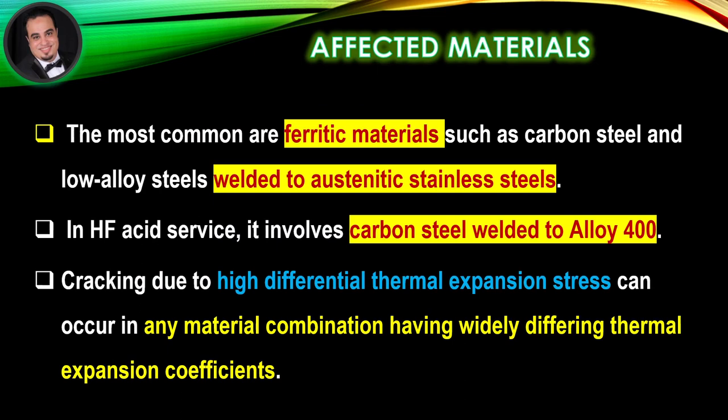Affected materials. The most common are ferritic materials such as carbon steel and low-alloy steels welded to austenitic stainless steels. In hydrofluoric acid service, it involves carbon steel welded to alloy 400. Cracking due to high differential thermal expansion stress can occur in any material combination having widely differing thermal expansion coefficients.